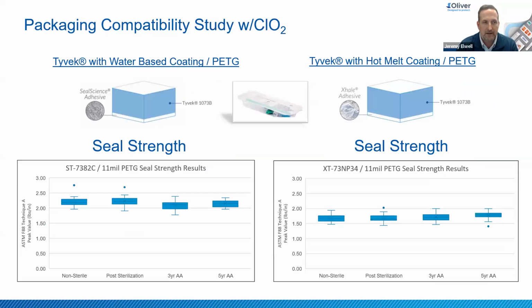And then we look at coated Tyvek with tray material, in this case, 11 mil PETG. So we're doing seal coupons. We're not taking fully formed trays in this study, but small seal coupons just to show seal strength over time and any kind of visual anomalies that we may see. But in this case, both a Seal Science or water-based type coating and an Xhale or hot melt type coating, they both showed compatibility and no adverse effects over time.